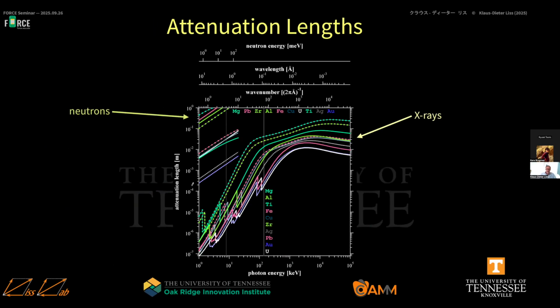This is just an example of attenuation lengths. Normal X-rays in the lab lie here. So this is in meter, this is micrometer, this is 10 micrometers. You see for many of the metals, you go a few 10 micrometers into the material. While with neutrons, they're all here for these typical elements. So you typically have centimeters to meters penetration. And for some of them, you have a little bit more absorption. So you're not going that deep, but still much deeper than the conventional lab X-rays.